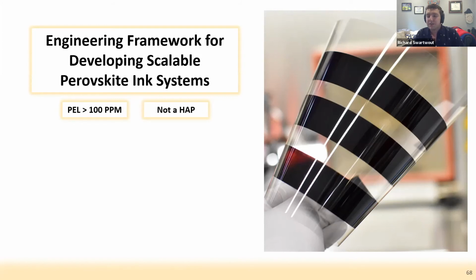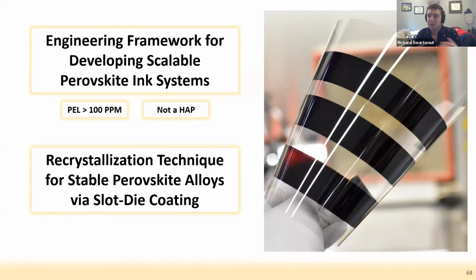I've also presented a novel recrystallization technique for easily translating small and large area perovskite films. I didn't talk about it too much today, but the power of this technique is that it's really alloy independent, and that it can achieve very high quality films with power conversion efficiencies over 20%.